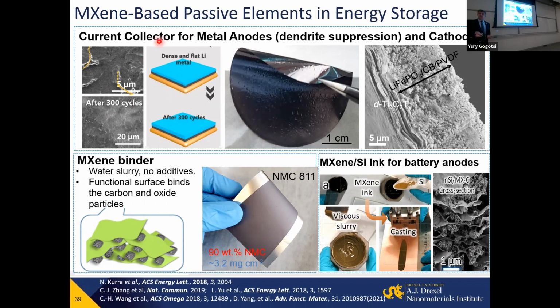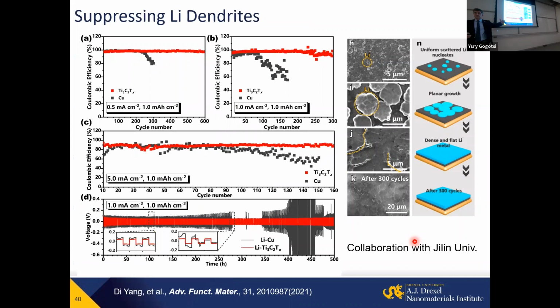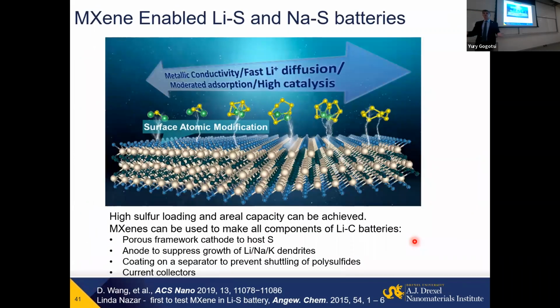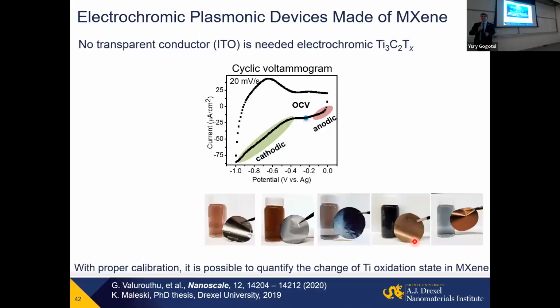So lithium or sodium grows parallel to the surface, which is again a very big deal in developing sodium sulfur, lithium sulfur batteries, and metal batteries in general. They can be used as conducting binder. So you can use a current collector, use conducting binder for cathode, anode materials, carbon, silicon anodes, and other applications. Again, I mentioned suppressing dendrite growth, making stable growth, adsorption of polysulfides, catalytic decomposition of polysulfides, and again, making conducting cathodes. Linda has priority in the field.